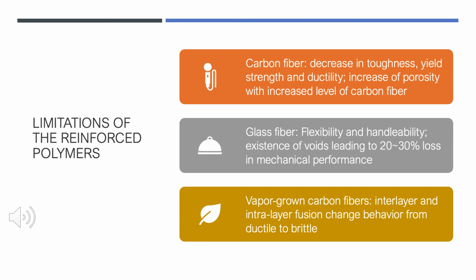Let's look at the limitations of the reinforced polymers. For carbon fiber, there is a decrease in toughness, yield strength, and ductility, and an increase of porosity with increased level of carbon fiber. And for the glass fiber, there are limits on flexibility and handleability, and the existence of voids leading to 20 to 30% loss in mechanical performance.